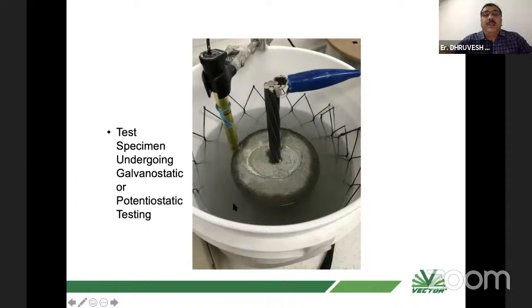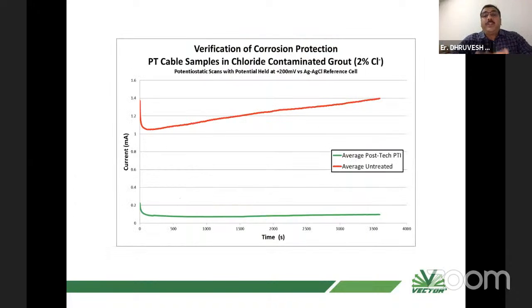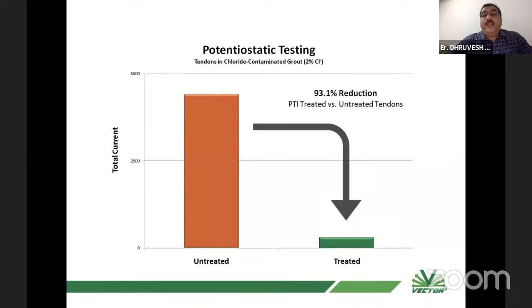With this whole system, the test was carried out, and it normally gives you the result of corrosion current. It was found that with 2% chloride concentration, the untreated sample's corrosion current was too high. And for the treated sample, we were able to reduce the corrosion current to a very low rate. So this shows that current was very less. It was protecting. There was very little corrosion. So definitely, for post-tension PTI cable, it really works. And when we quantify it, we can find that there is a 93.1% reduction.